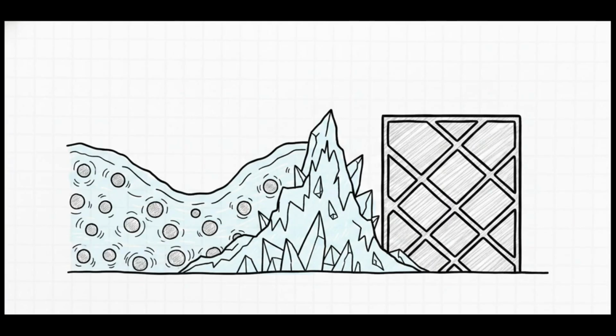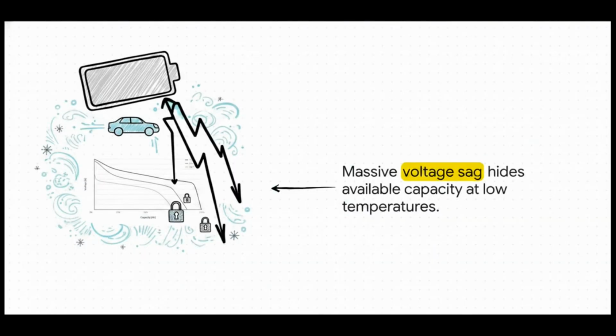The lithium ions are physically struggling to get out of that liquid electrolyte and embed themselves into the solid structure of the electrode. And this brilliantly illustrates the real-world consequence of all that resistance: massive voltage sag. Notice the huge drop in the curves at 0 and -20°C compared to that optimal 30° baseline. When your vehicle demands power, that high internal resistance causes the voltage to heavily dip under load.